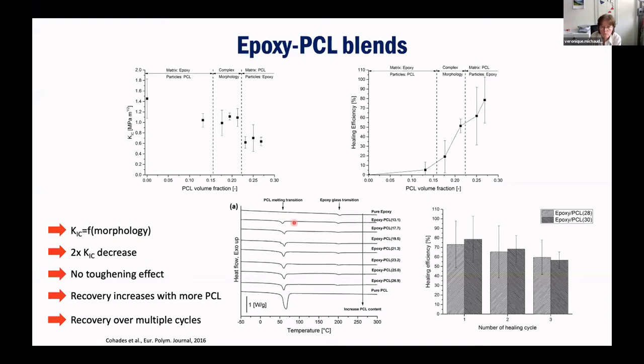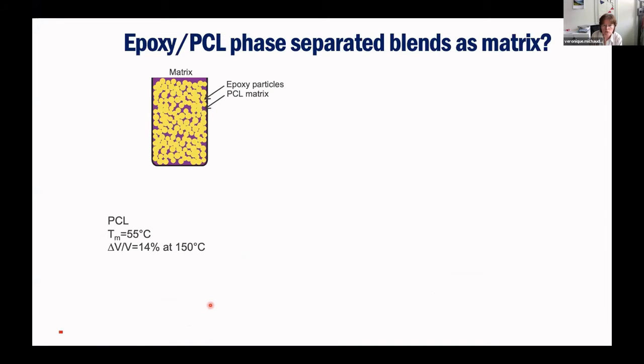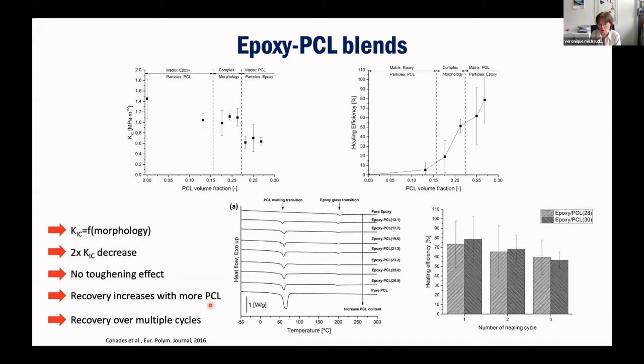This time we also looked and clearly saw that we still see the PCL melting transition. So it's really a phase, no miscibility of each phase. We can see the epoxy glass transition in that case. And we saw that we could actually heal and reheal several times the same TDCB samples. And we lost a bit of healing efficiency, but it can still be done several times. So this was in 2016, and okay, we were happy.